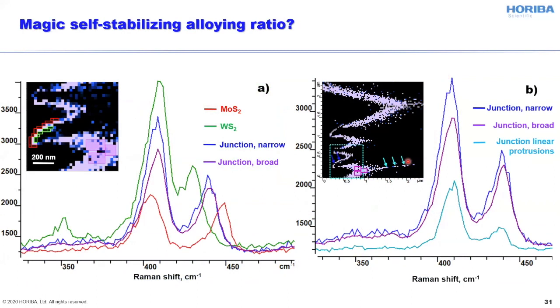Okay, now let's talk about the spatial resolution and another interesting observation that we made in the TERS imaging of these lateral heterostructures. As we discussed already earlier, the width of the transition area was quite different along the heterojunction of the same crystal. And we can clearly see that when we integrate and average the TERS response of the spectra on the tungsten disulfide side, immediately adjacent to the transition area, molybdenum disulfide, and the pixels in between corresponding to the transition between molybdenum disulfide core and tungsten disulfide shell, we have very clear signatures of tungsten disulfide, molybdenum disulfide, and this transition area.